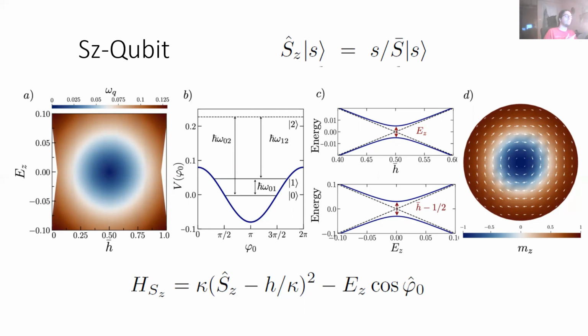And at the B section, you see that the anharmonicity actually exists in this energy and helicity diagram, because we know that the system is topologically protected, which means that when we look at its phase φ0 at the bottom of the B section, the system will be the same in each 2π of turning. So we know that the φ0 ket is equal to the φ0 plus 2π ket. This makes the system protected.